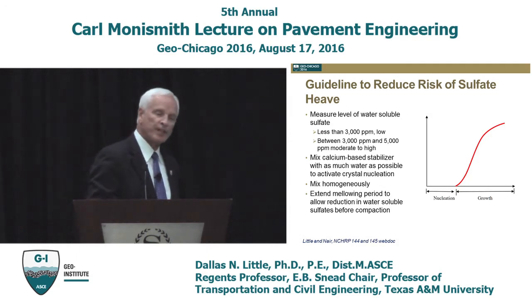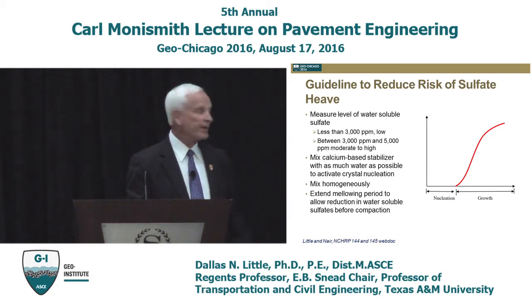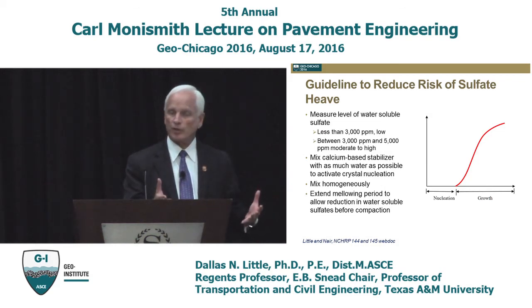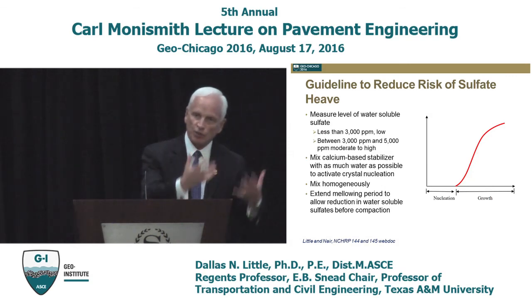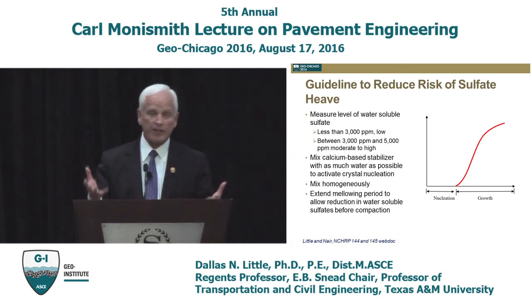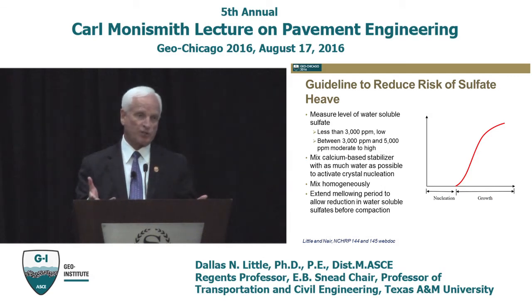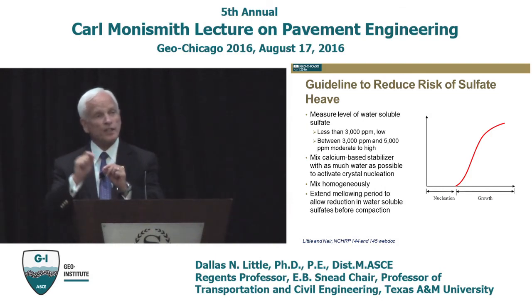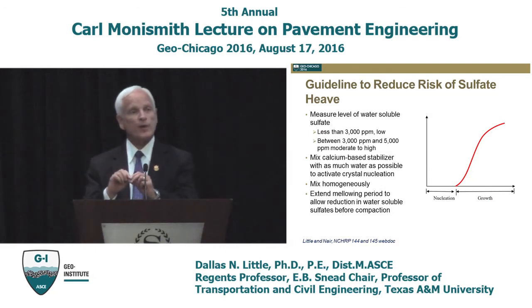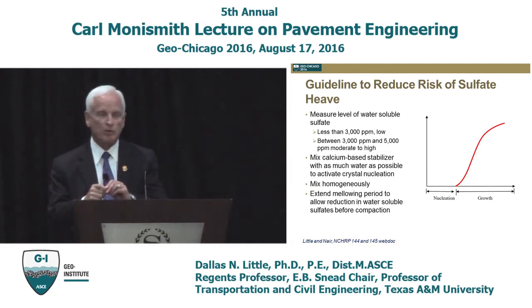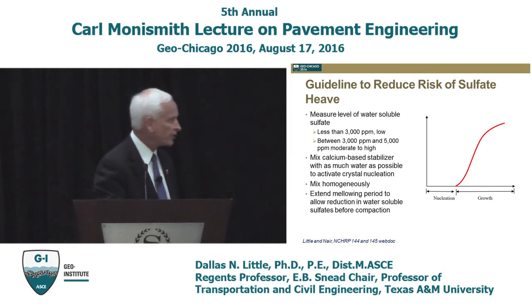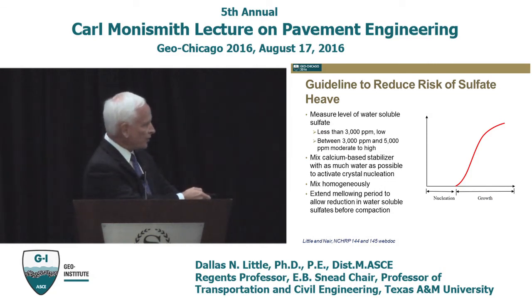So what we want to do, basically, if you have sulfate-bearing soils in this range, you want to add as much water as possible to activate the solution process of sulfate. You'll never add enough water to solubilize it because the solubility coefficient is too low. But you want to add enough to begin the process. So you start to nucleate crystals of ettringite, which form very rapidly if all constituents are available. You start to nucleate these points. And with any type of crystal, you have to nucleate before you can grow. So you nucleate the crystals and then the crystal growth occurs.